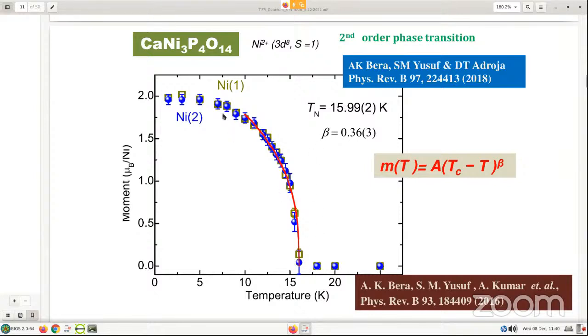We have also done the critical exponent study, and how this spontaneous magnetization, the ordered moment, builds up as soon as the magnetic phase transition takes place, with the critical exponent beta found to be 0.36. And what is shown here is that both nickel 1 and nickel 2 are almost approaching the full value as expected from a spin 1 system.